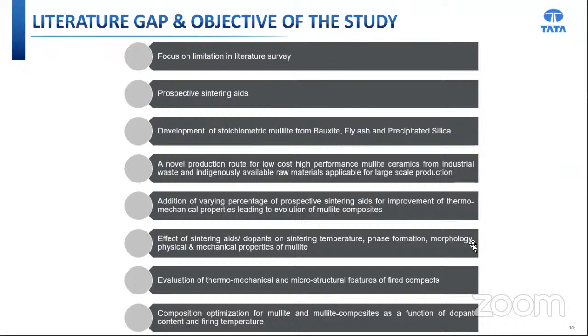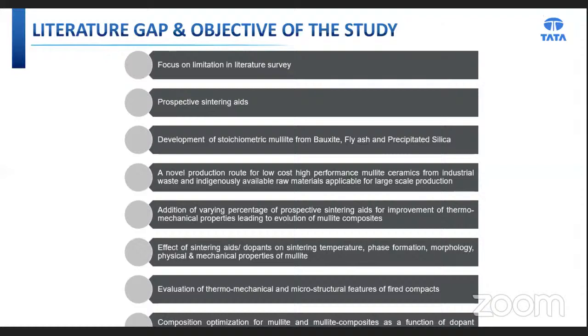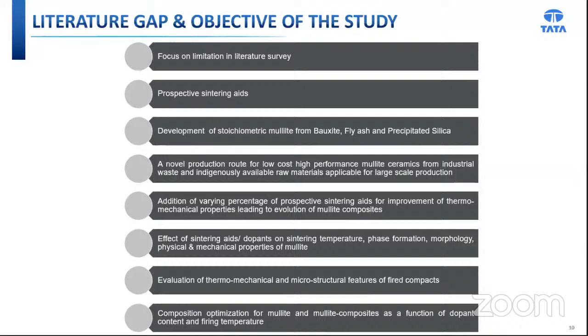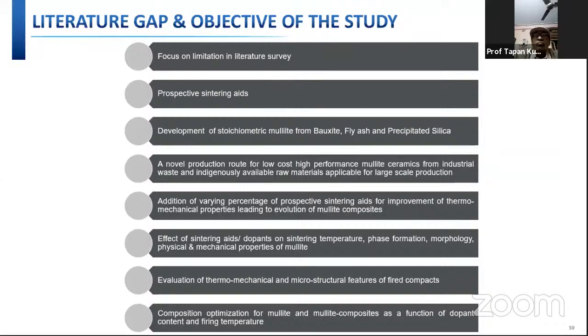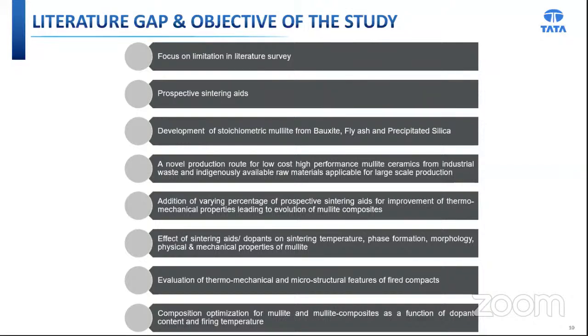The third one: in order to achieve good quality mullite by solid state sintering, we have to achieve the optimum properties with smaller particle size. The fourth one, it is cost effective. The fifth one, it is an effective utilization of naturally occurring abundant materials. The sixth is that it is environmentally friendly because we are using fly ash. A lot of fly ash is produced in India, almost 250 million tonnes per annum. Out of 250 million, 78% of fly ash is used, but the remaining 22% is dumped. I don't know whether it is maintaining the environmental norms. So if we use at least 0.5 or 1% of this fly ash to produce this material, it will be helpful and environmentally friendly.